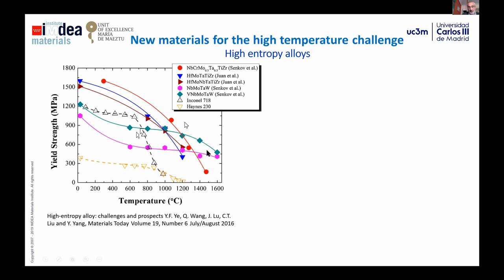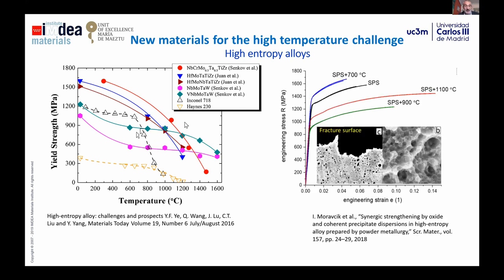But these high entropy alloys, of course, can be produced by ingot casting, but also by powder metallurgy. But by powder metallurgy, we can do things that are not possible to do with conventional ingot casting. For instance, the development of the so-called ODS high entropy alloys, in which we can disperse oxides in the high entropy alloy through spark plasma sintering and other powder metallurgy technologies. We can reach exceptional tensile features in comparison with conventional ingot metallurgy high entropy alloys.